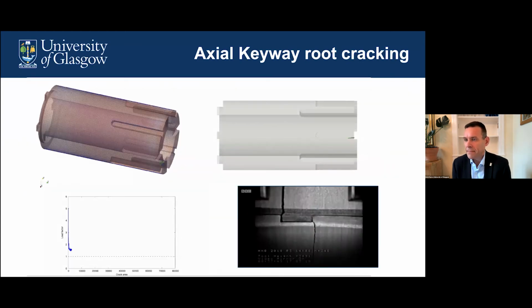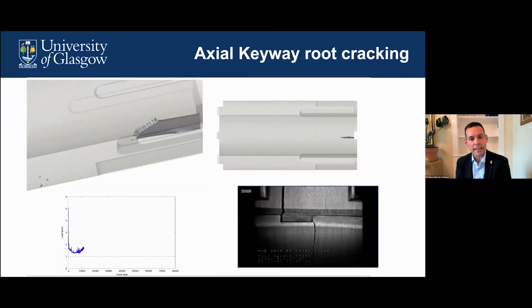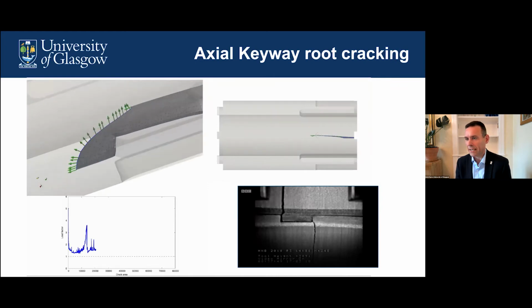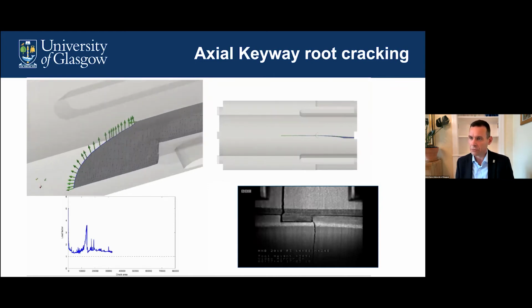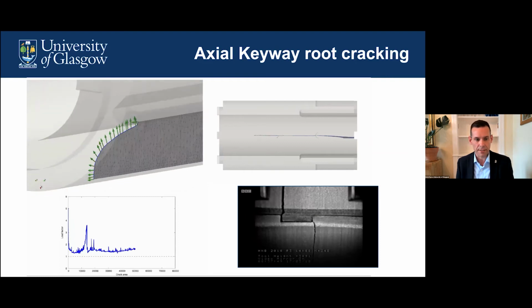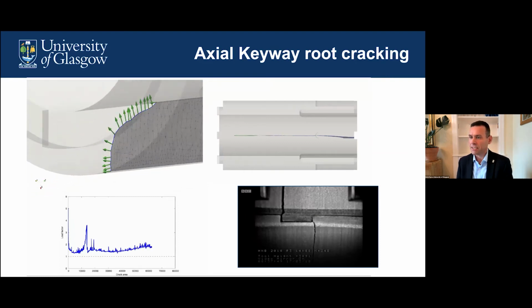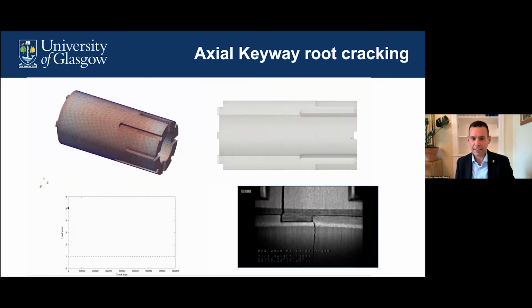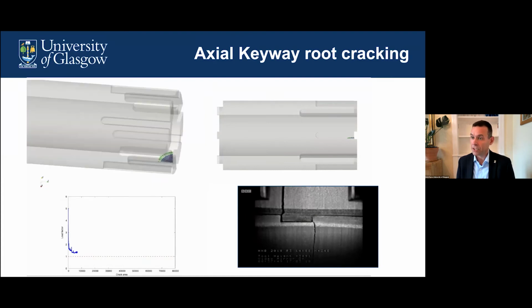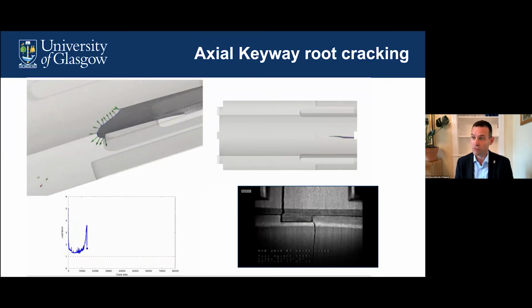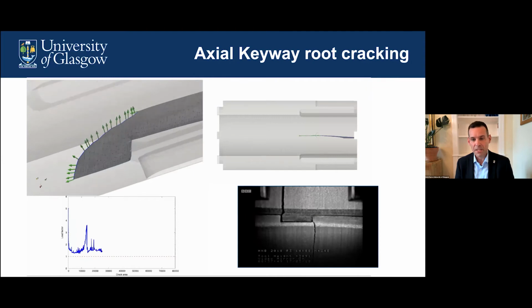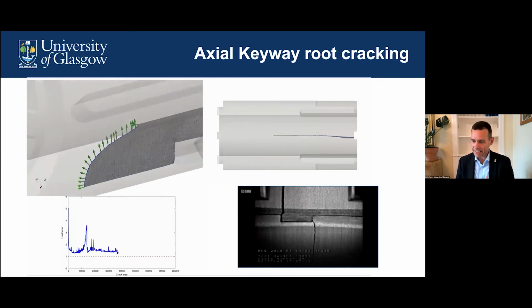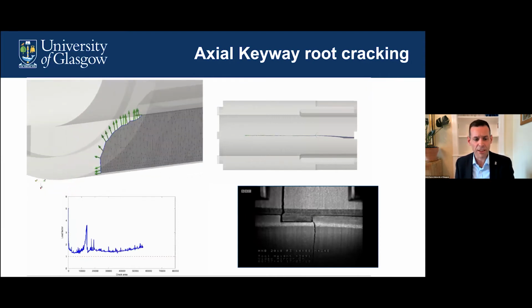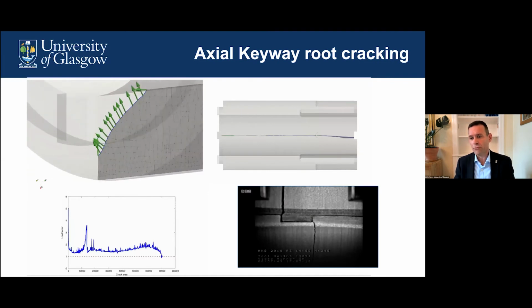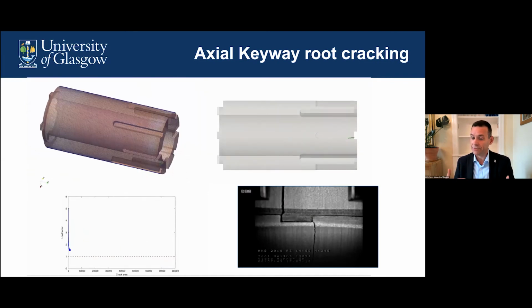So this animation is showing the crack propagating along the length of the brick as a result of scaling the internal stresses. On the top left, you can see an animation of the crack propagating. You can see the green arrows are the configurational forces that are the driver for crack propagation. You can see it negotiating this complicated change in geometry.